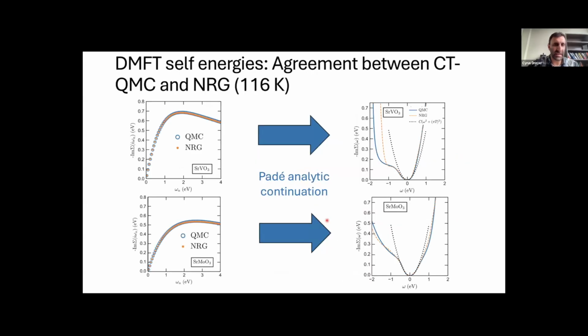And so here are some calculations of the self energies on the Matsubara frequency axis, and then the Pade analytic continuation to real frequency. And we can see that in both cases, at least at low frequencies, the continuous time QMC and the NRG agree very well with each other. And I'm brushing over a lot of computational details and headaches that made this possible. But this gives us confidence not only in the solution to the impurity problem, but also in the analytic continuation at low frequencies. Though I'll show that actually this agreement is not enough to get converged scattering rates.